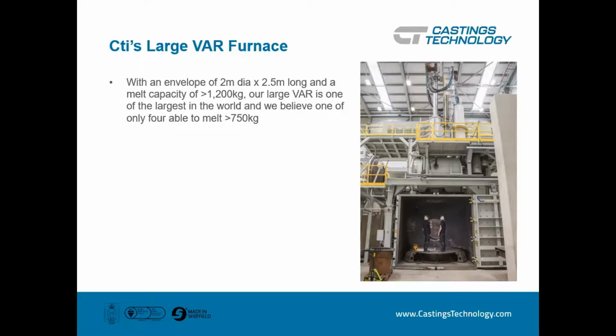So what basically happens is vacuum arc remelting, which starts with an electrode as its starting stock, unlike most of our other materials, which start as scraps and offcuts. We're starting with an electrode that is 2.2 meters long, 585 millimeters in diameter, and it has a stub at the top that the crane can hold on to. That's a 40,000 pound ingot of titanium. We pick it up using the hydraulic ram at the top and put it into a vacuum chamber, which is over the top of the melting chamber.